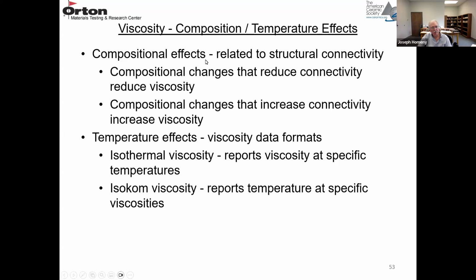So the composition effects are related to the structural connectivity. Anytime a compositional change reduces the connectivity and creates more non-bridging oxygens, you reduce the viscosity. And anytime the compositional change increases the connectivity and increases the bridging oxygens, that will increase the viscosity. So for temperature effects, there are two ways to describe the viscosity. One is isothermal and one is isokom. In isothermal viscosity, you're reporting viscosity at a specific temperature. In isokom viscosity, you're reporting a temperature at a specific viscosity. So it's just the reverse.